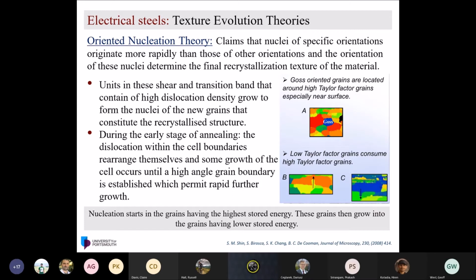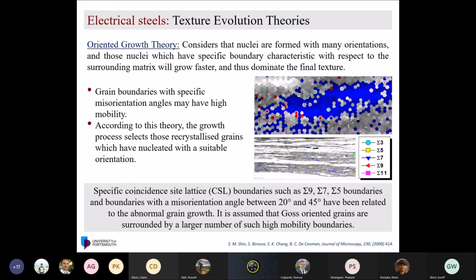When you have high dislocation density, you can have a high Taylor factor, so you will have more stored energy. So a grain like Goss has less Taylor factor, and it will consume the grain with high Taylor factor. So that's the nucleation starting, and that's supporting the theory of the recrystallization stage. And next. The other theory is oriented growth theory.